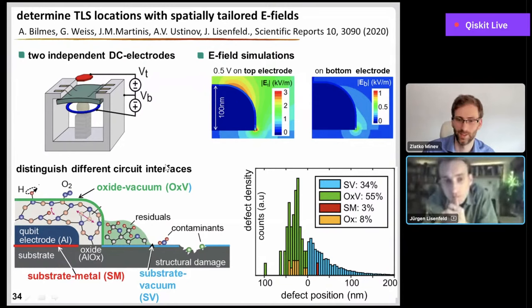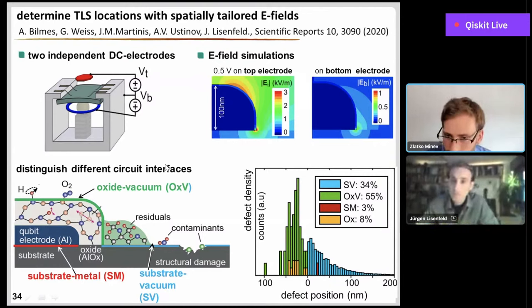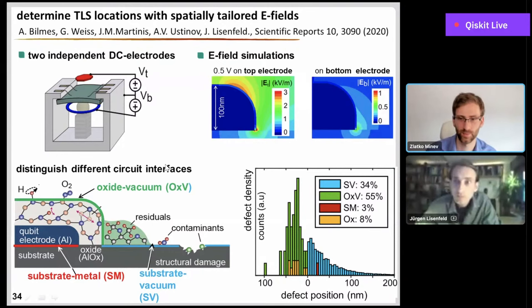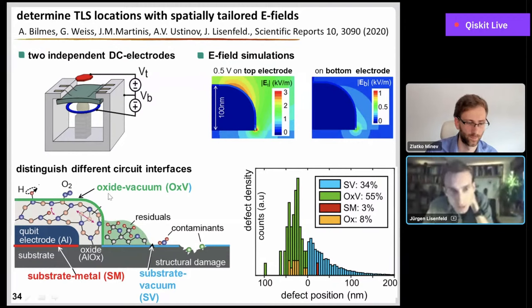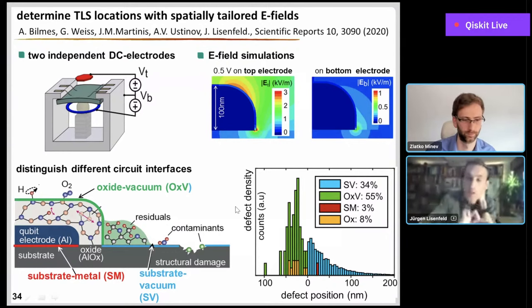Yeah. Great. Quick question from the audience. How did you make sure whether a defect comes from the oxide but not the oxide vacuum interface? Yeah. We find all defects here actually sitting basically on the oxide vacuum interface. So on the very surface of this oxide. As I said, simply because inside this dielectric, we would expect smaller coupling strengths for the defects than we find. And that's why the possible solution for this defect position from our analysis was mostly here on the surface.